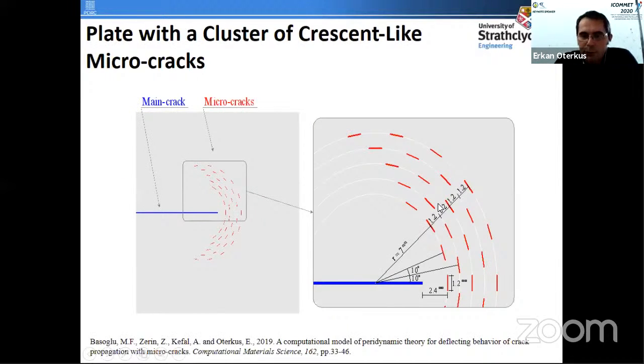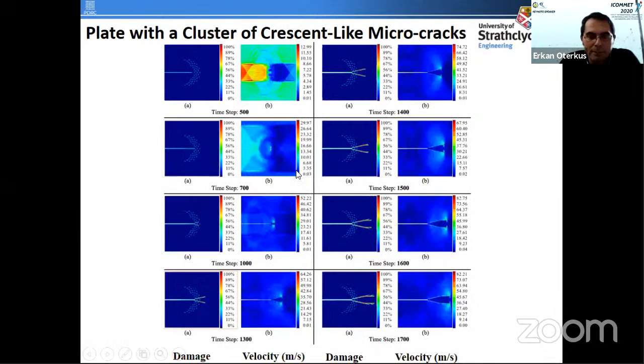Also, as I said, peridynamics really doesn't care about how many cracks we have in the system. So this is an example like this. We have a big macro crack here, and there are small micro cracks around it. We want to see how these cracks are influencing the propagation of the macro crack. Again, peridynamics is a very suitable tool for this. These plots are showing some peridynamic results, which show how the crack is propagating and how these small cracks are influencing the propagation of the macro crack. So as you see, if you use peridynamics, you can have as many cracks as possible, and you can investigate how the cracks are interacting with each other.